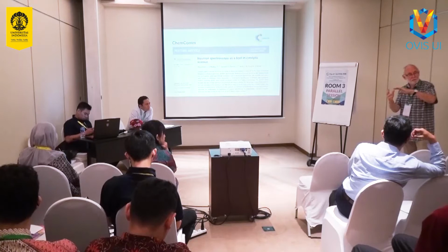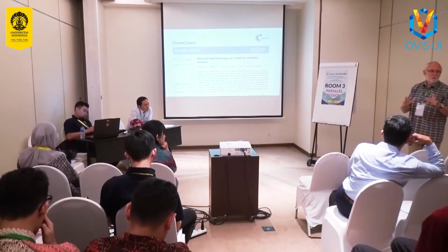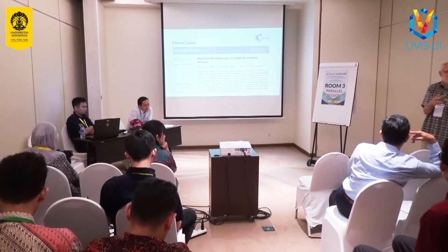What we've discovered is that if we use catalyst at 400 degrees, we're actually making the pores bigger because we're partly steaming the zeolite, and that's what we learned. But methanol is not a great probe because it's also reactive. Even if we're only putting it in at room temperature, it's a little bit too strong. And we're now going to do those experiments with methane. Methane will not react. We can look at the mobility of methane. We just want to learn about how much empty space is still available in the zeolite. We should put in a molecule which is less strongly bound than methanol. But we didn't know that when we started. So now we're looking to do that.